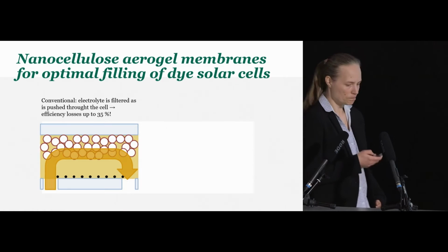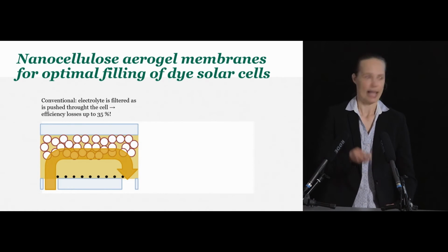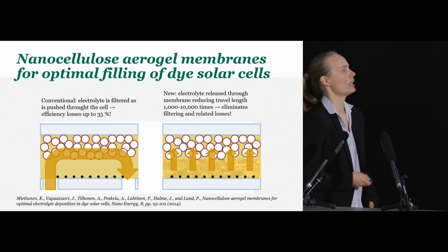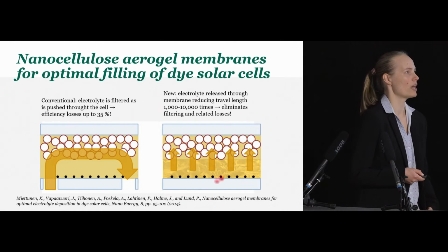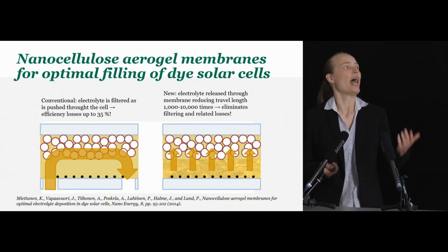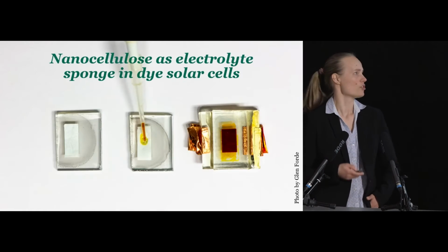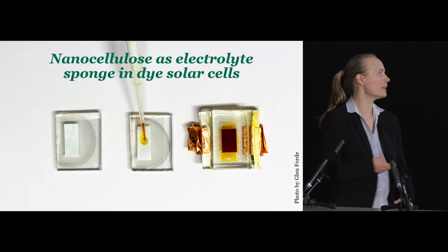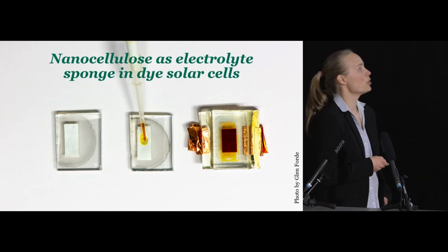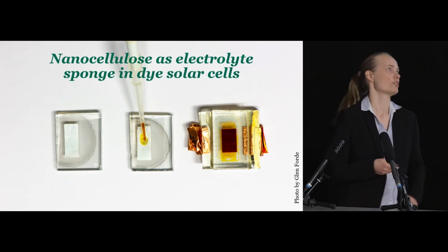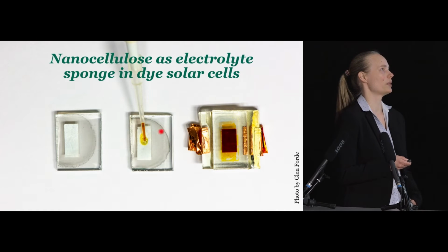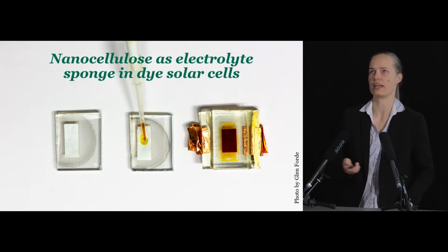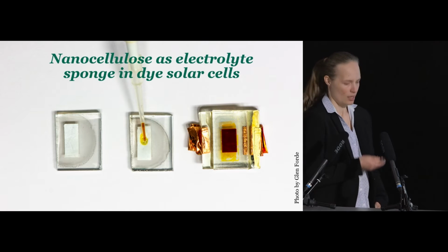into the cell. What we did instead was that we actually screen printed cellulose nanofibrils on top of the counter electrode. We freeze-dried it, and then we got these type of sponges that are pictured here. And these sponges could then act as electrolyte supports. So you can just drop a droplet of electrolyte, and it spreads really nicely on the cellulose film.